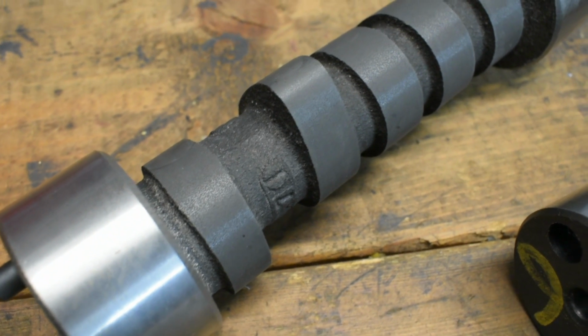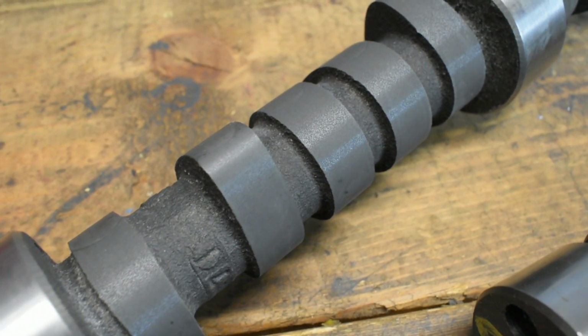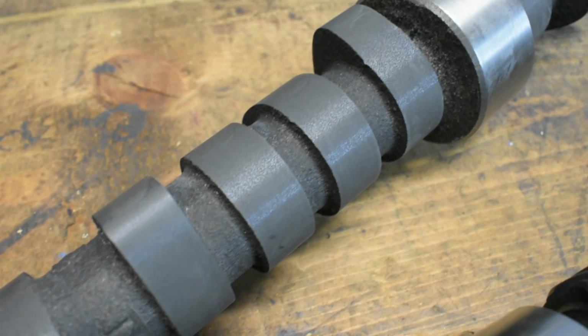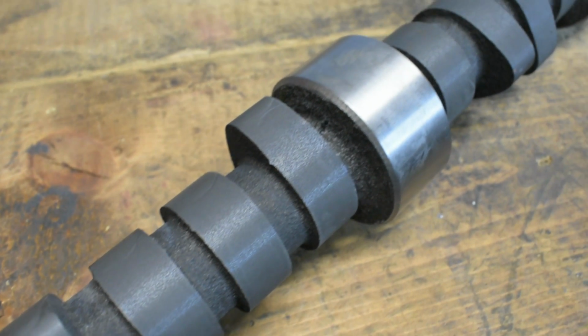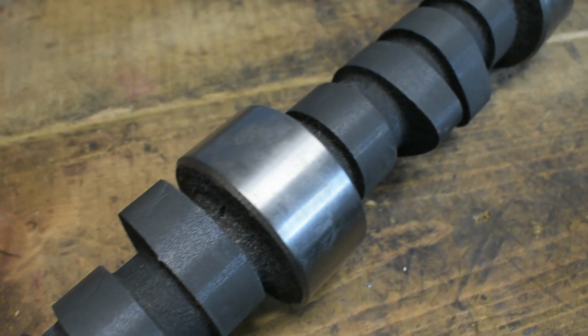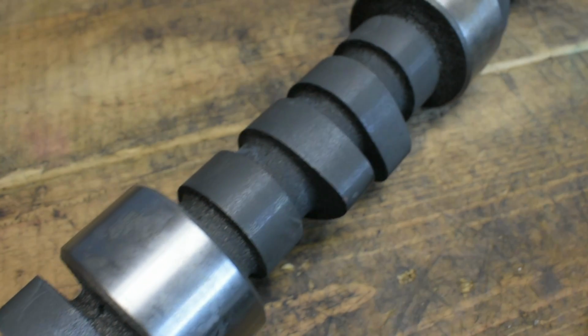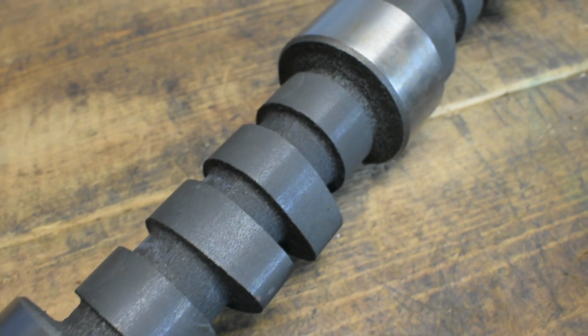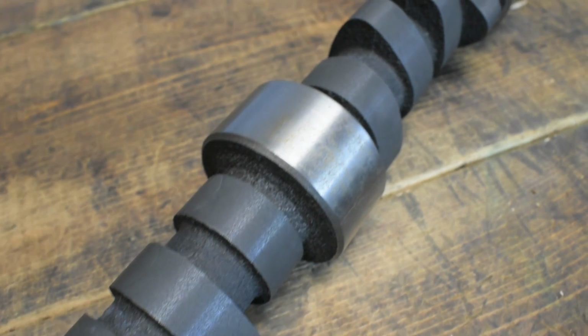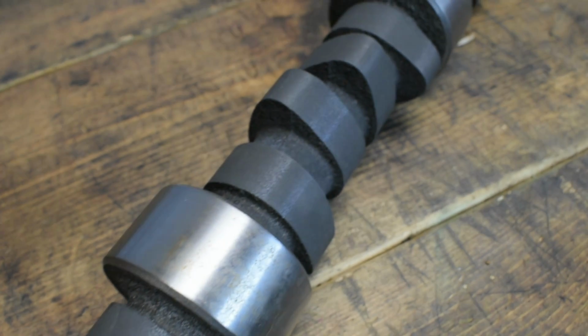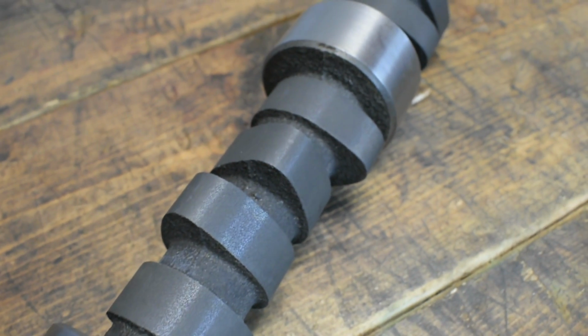Now, if you have a hardness of around 50 on the surface, it typically will let that cam supplier know that the depth of the heat treat has gone deep enough in it that they can grind what they need to grind on it. If that's less than that, if it's a 45, that means that the heat treat may not have got deep enough in there.